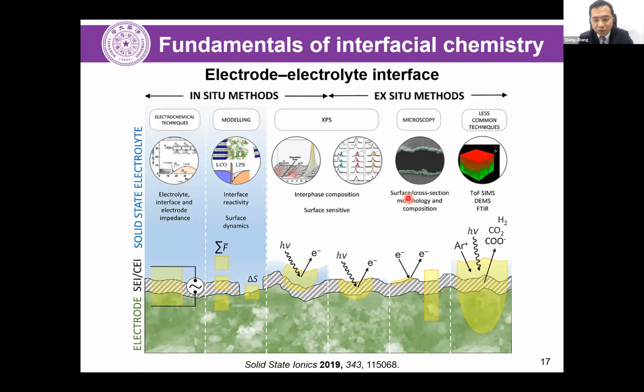For example, we can use some electron or X-ray beam or some light to touch the surface, and then we can get the feedback about the composition, about the bonding, about the chemical composition of the surface. We also can sputter the surface and get the depth profiles. And also there are several molecular modeling methods which can provide the information about the electron structure, while the electrochemical technique can probe the ion conductivity and electroconductivity of the working interface.